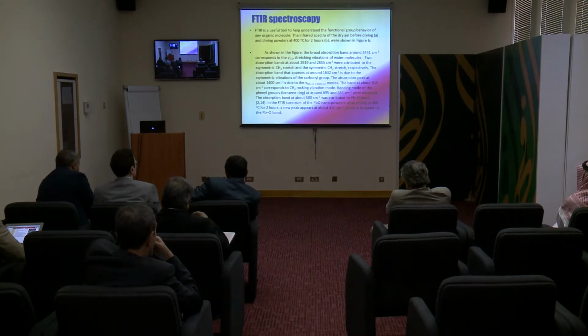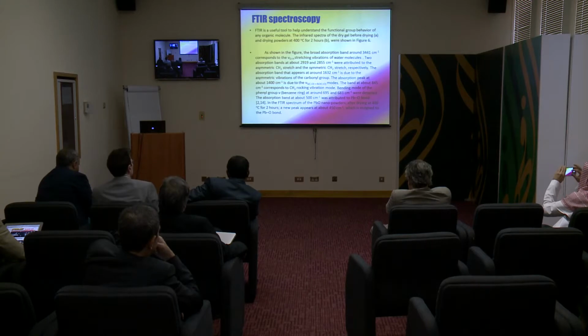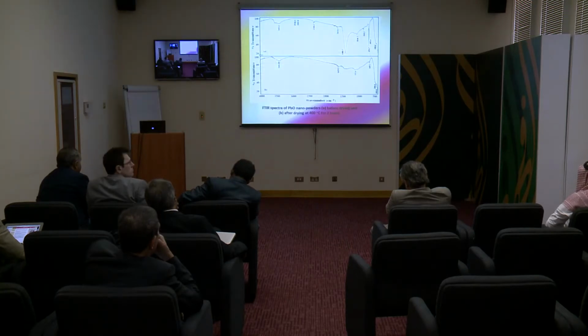FTIR used before annealing and after annealing. So FTIR is a tool to understand the functional groups of organic molecules. Infrared spectra of dry gel before drying and the dried powder at 400 degrees centigrade for 2 hours, as shown in this figure. FTIR spectra confirm that a new peak appears at about 450 in wave number, which is suggested to be the PbO bond, lead oxide bond.